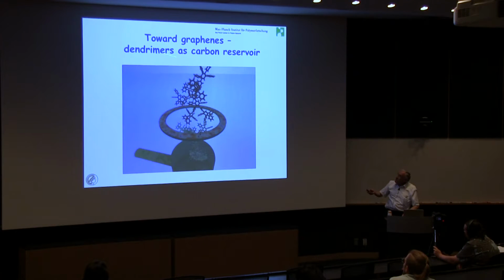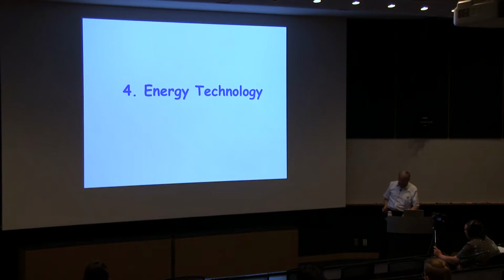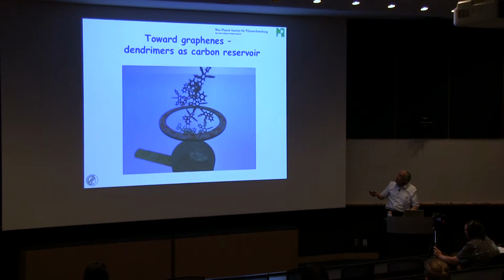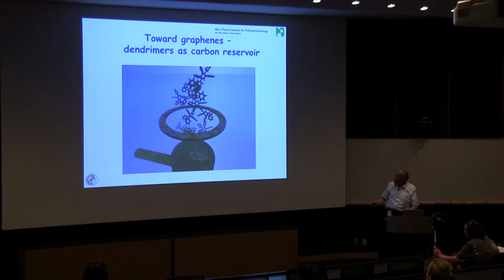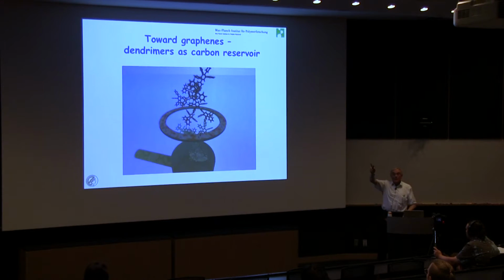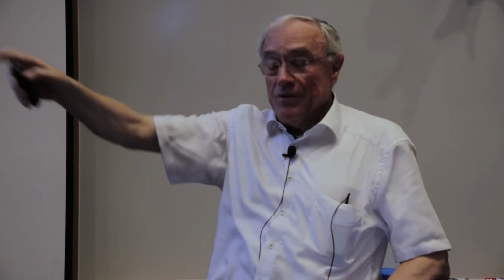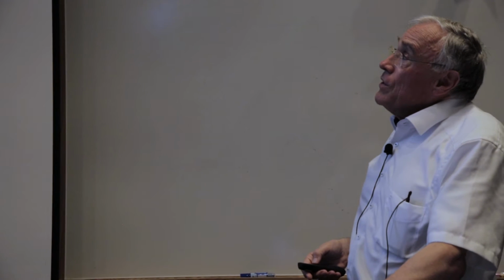So, regarding the carbon structure, we start from a three-dimensional precursor, and this is the art of synthesis. And we planarize that. I could show you that this is planarized, and this explains why dendritic precursors are now the source of beautifully designable and perfect graphene structures. The energy technology.